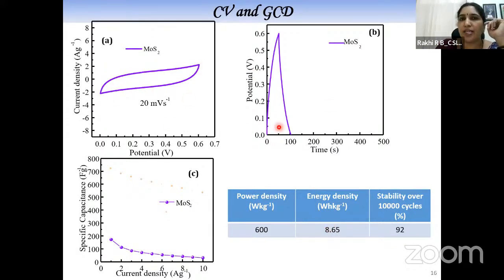We got CV, CD curves like this, and the capacitance value calculated was nearly 200 farad per gram. So, okay, we can confirm that this graphene also we used like that only. We used to take graphene, make the electrode the conventional way and test it. So the system gives performance matching with that of the graphene, so I can proceed with this one. So I am confident. Then we checked the power density and energy density, then stability. Stability for the collected deposit was more than 92%.